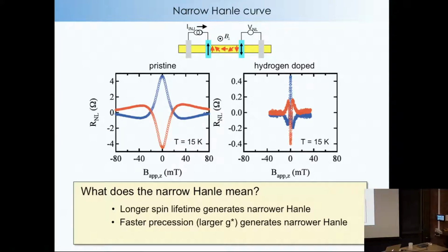But wait a minute. It turns out that's one way to make a narrower Hanle. Another way is if you had a faster precession, you'd also get a narrower Hanle. So how do you know which one is which? There have been papers that reported really long spin lifetimes, but in fact it's probably this effect going on. So this is a real problem within the field. How do you interpret your data?